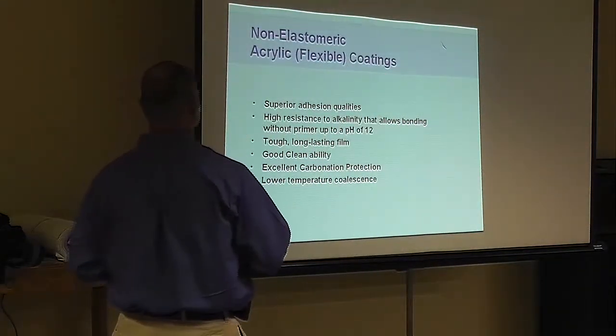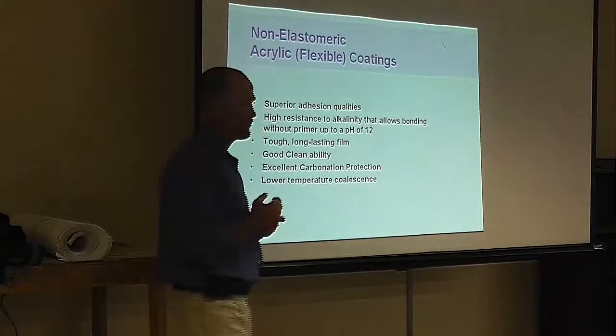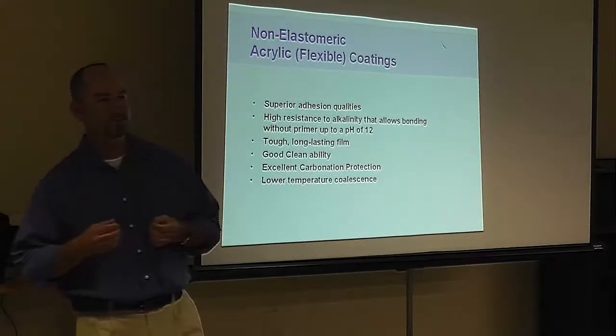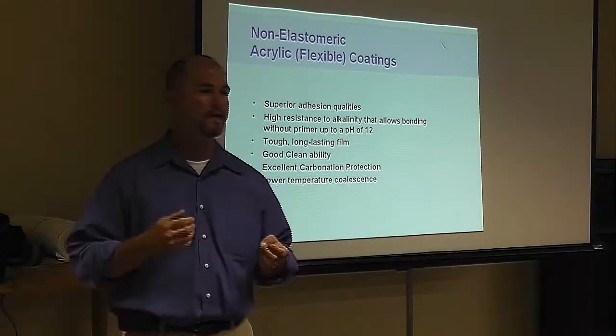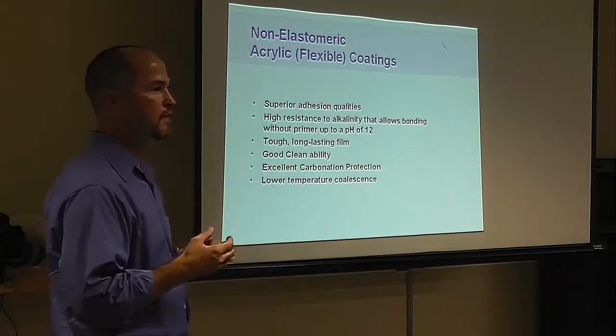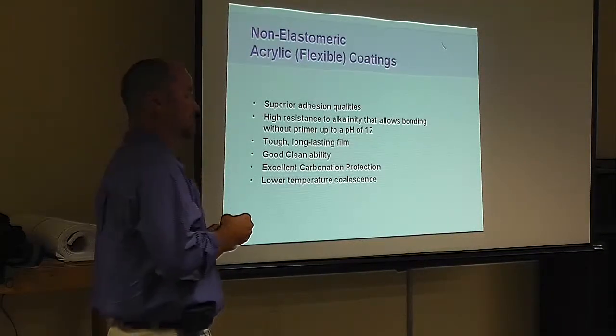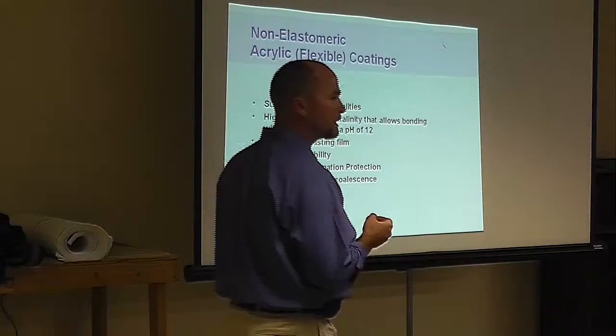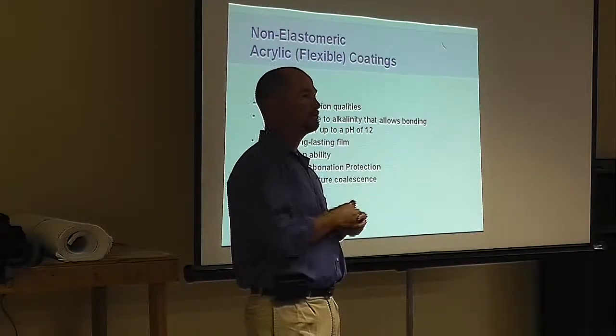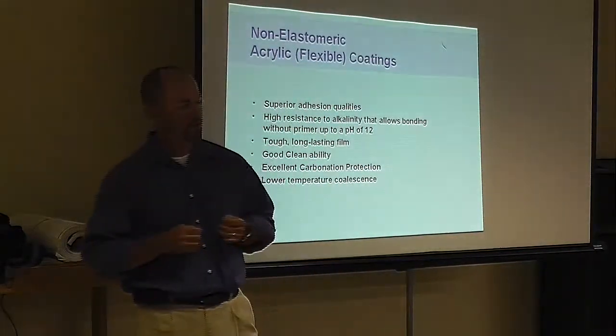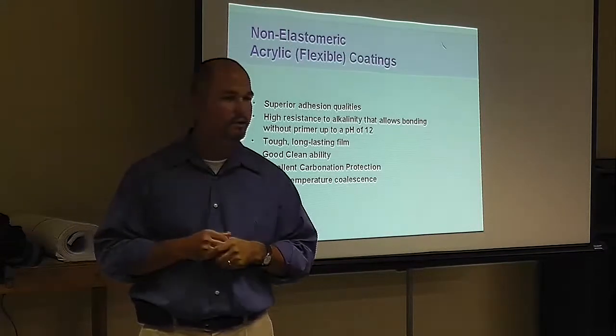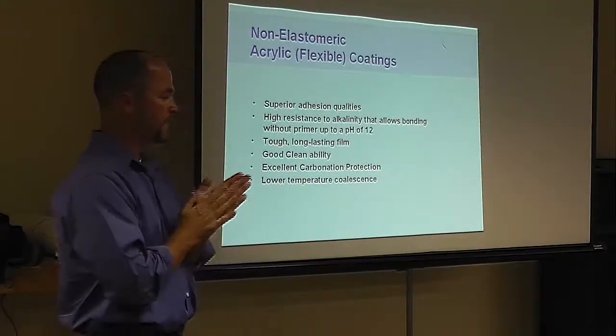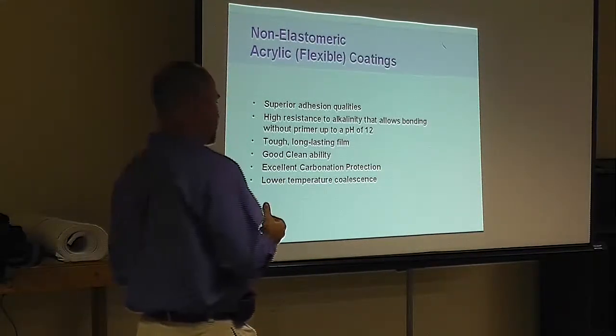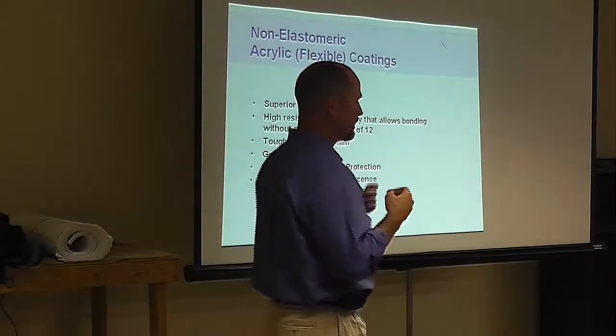Non-elastomeric acrylic coatings can coalesce at lower temperatures. They can handle a higher pH, especially if you've got some patching done on a job. Your high build coatings can handle a pH right around 12. A lot of times with patching, I'll come out and do a pH test, but they need to get it done, so I switch them to high build coatings when that type of application needs to happen. They've got superior adhesion, especially to slicker surfaces. They bond better than your elastomerics do.